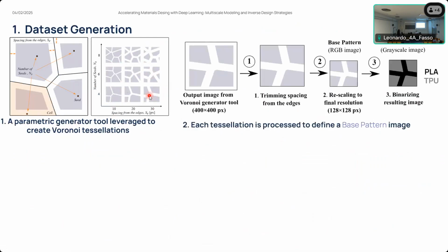The images generated with this parametric tool are then processed in order to obtain what we call the base pattern image. This is the image to which we assign the material properties. How do we encode them? Pixel values represented by black color represent the stiffer phase of the composite structure. So PLA material, polylactic acid, is represented by black pixels, and the TPU, the thermoplastic polyurethane, is encoded in gray pixel colors.